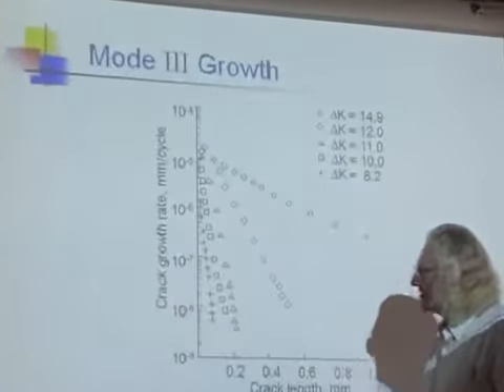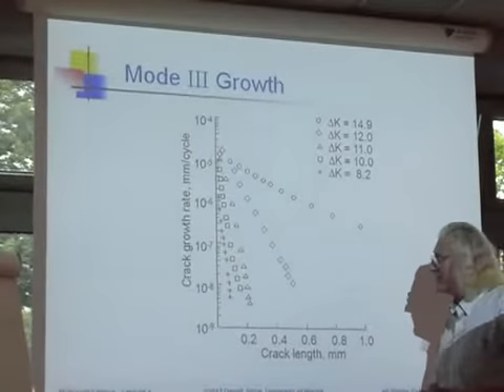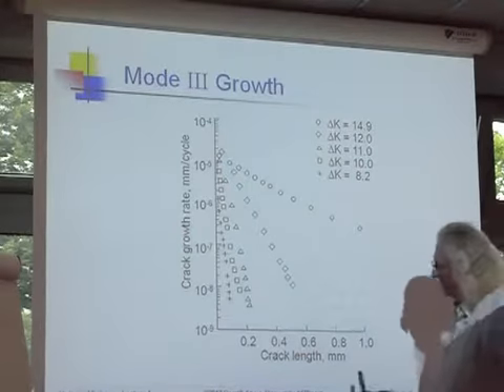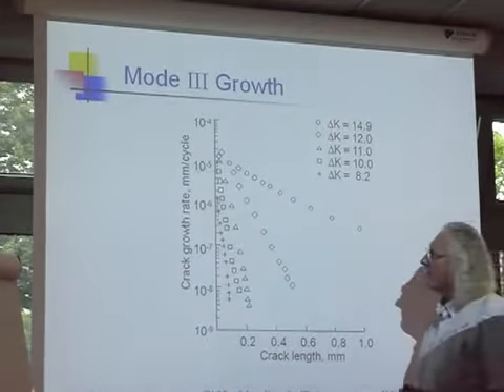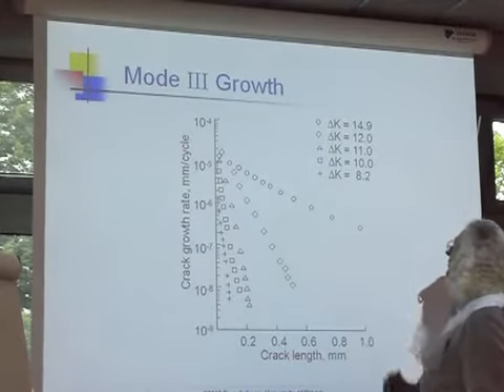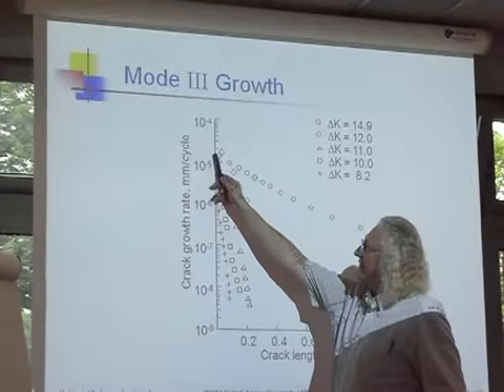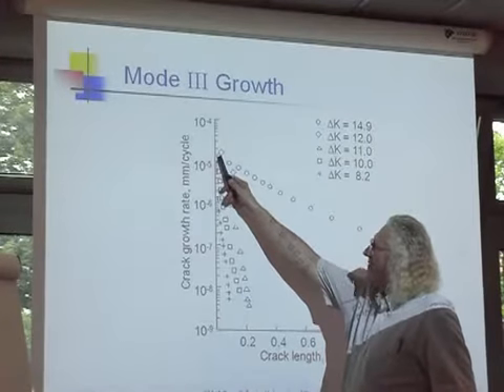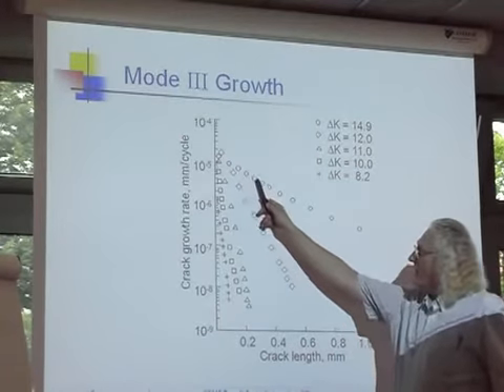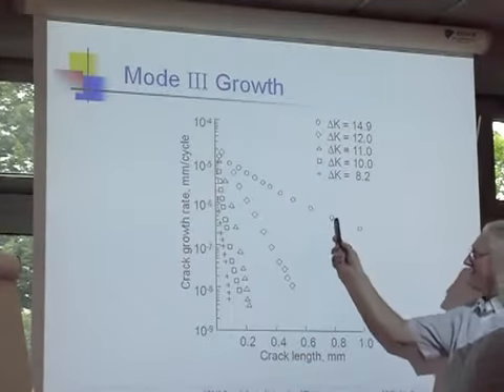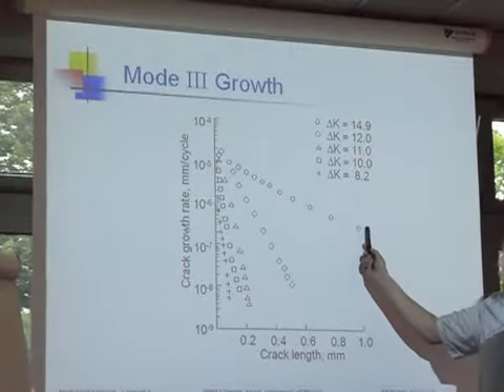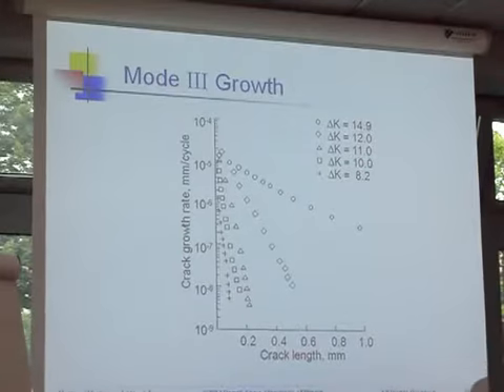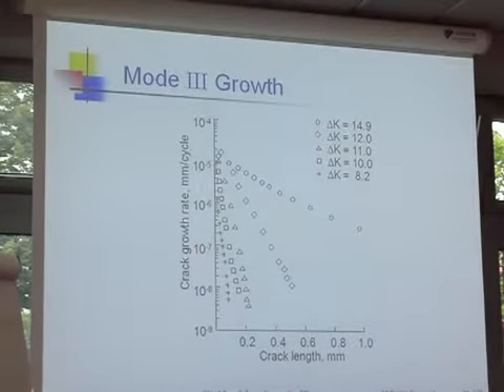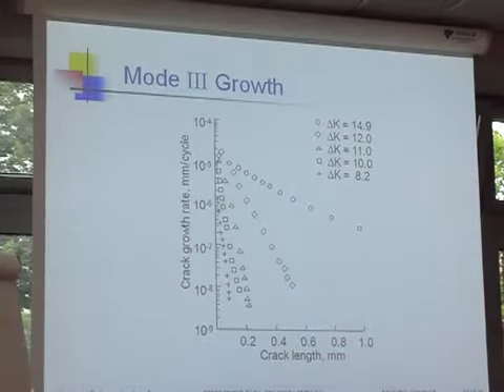So here's the crack growth rate. Very careful experiments. And these are done at different values of constant delta K. So here are the values of delta K, and look what happens. So here is the crack length out to the first millimeter. And these start off with the stress intensity, for example, the circle stress intensity of 15. I start off and I maintain the stress intensity constant. And okay, it grows pretty fast, but look, as the crack starts to grow and grow, the growth rate becomes less and less, and it's changed now by at least an order of magnitude. And why is that? When the cracks are really small, there's not so much friction. But as the cracks grow larger and larger, the fracture surface becomes more and more irregular, so I build up more and more friction, and so the cracks keep slowing down.